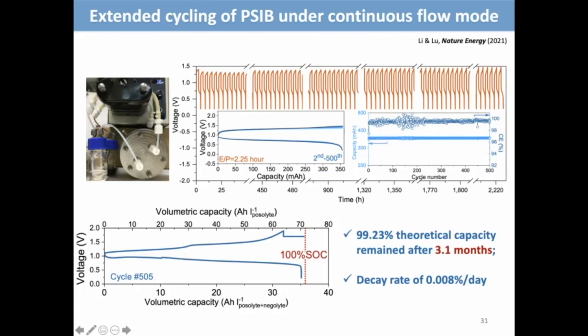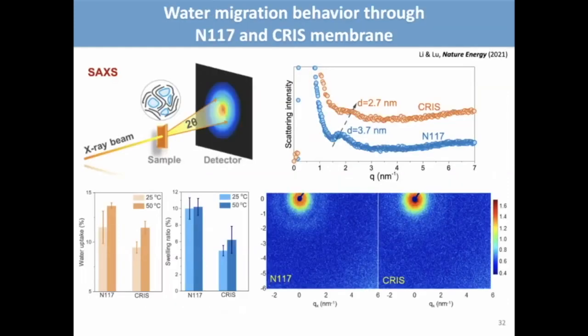So the decay rate for the flow battery is about 0.008% per day, which is quite similar to that of the static mode, which shows that they are quite consistent and stable, whether it's flow or not. So we want to understand what makes it so different between this membrane and the commercial membrane.